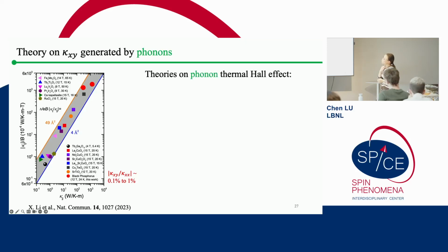But what I want to show you here is that, in general, the theories about the phonon thermal Hall effect can be loosely divided into two different categories. If you check the literature from about 20 to 30 years ago, they will directly tell you phonons have no thermal Hall effect because phonons have no charge and no spin. So how could they couple to an external magnetic field to give you a Hall effect? This means phonons have to couple to something else, and that thing couples to the field to give you a Hall effect. The first category, we call an intrinsic effect, which is based on the coupling between phonons and their pristine environment. For example, coupling between phonons and magnons, or just general spin-lattice coupling, can give you a non-zero phonon thermal Hall effect.